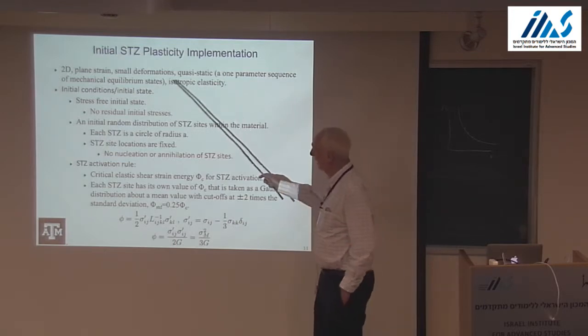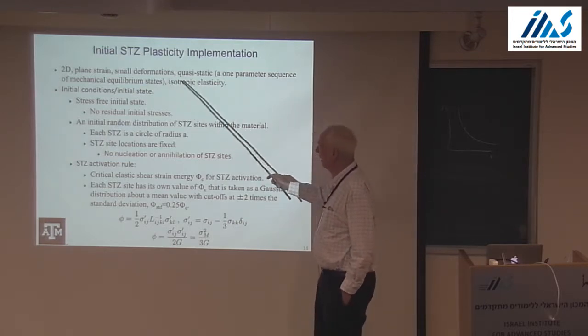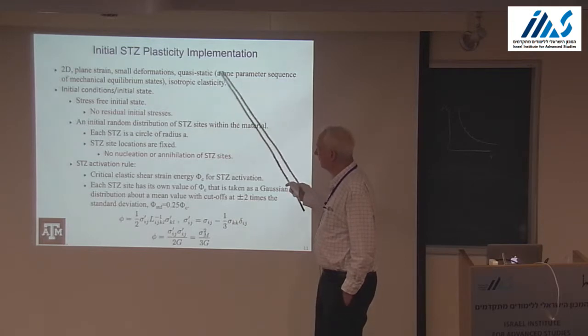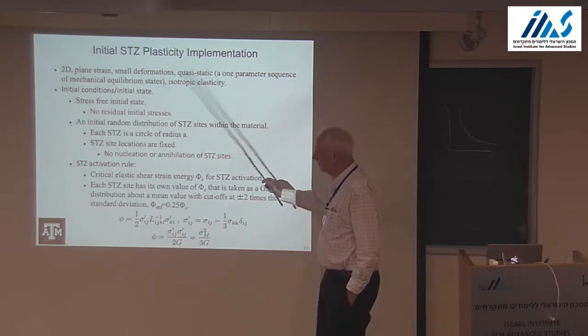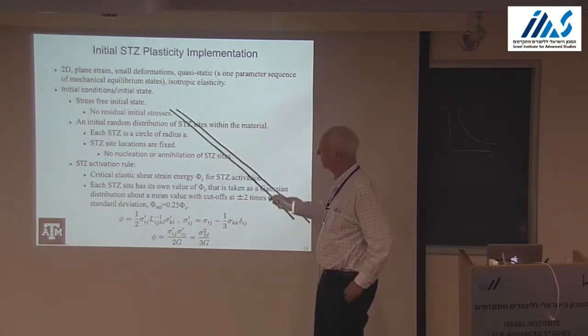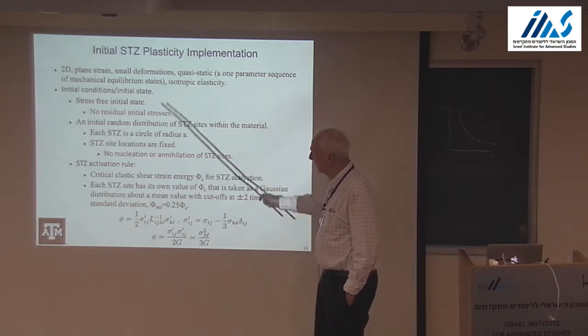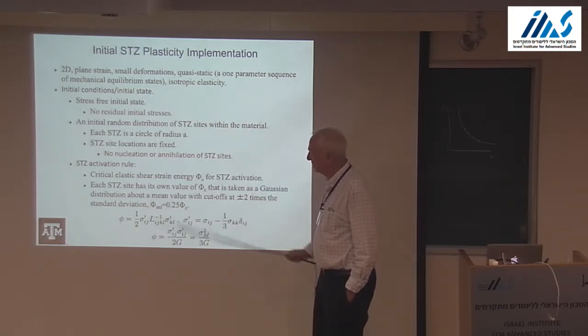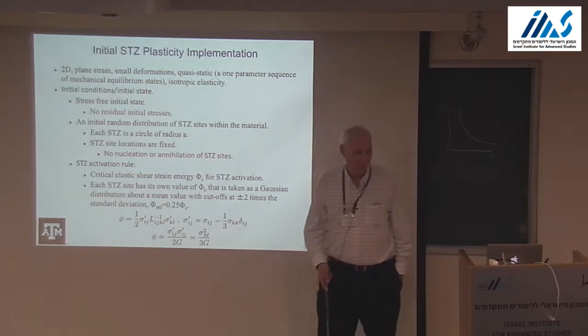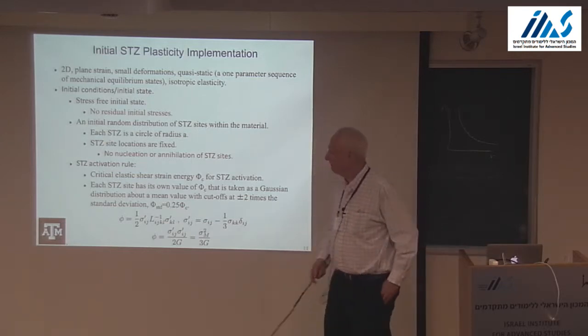Okay, so I'm going to talk about 2D plane strain. Again, by quasi-static, I mean a one-parameter sequence of mechanical equilibrium states. Isotropic elasticity, so no residual initial stresses. That's probably very important. We could add that later.